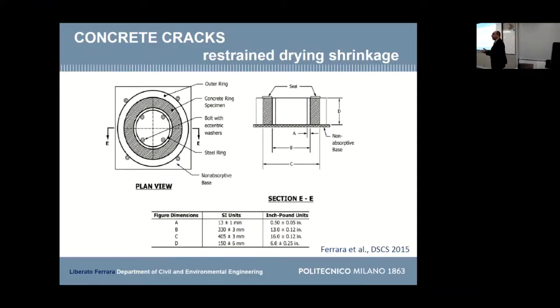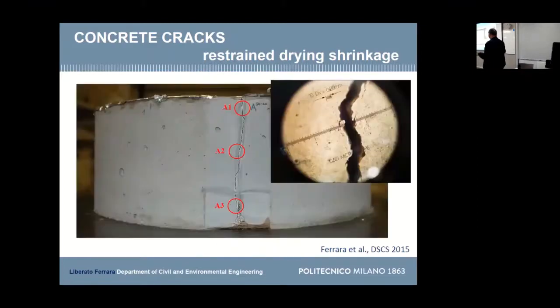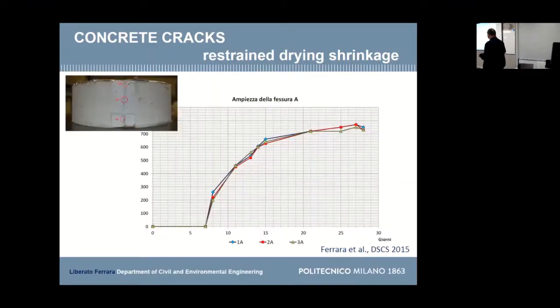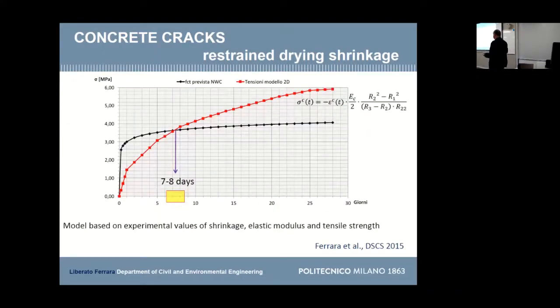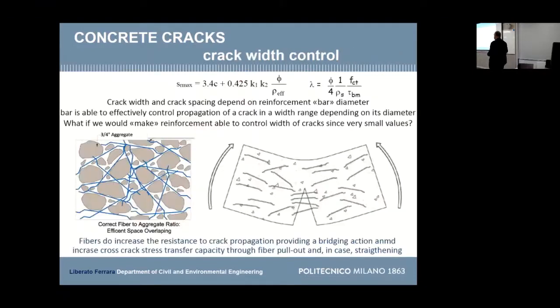And similar things you may do with restrained drying shrinkage, which also occurs probably even before you put the structure under loads. And this is the ring test. You can see here some images. In this case, the cracks appeared 7 days after casting, which is not so early, but still it's before you complete and you put into service our structure. And you also have models to predict the appearance of the crack, because you can build up your strength development curve and you calculate with linear elasticity formula the stresses in the ring from the strain gauges that you put, and when the curves meet, you find the cracking moment.